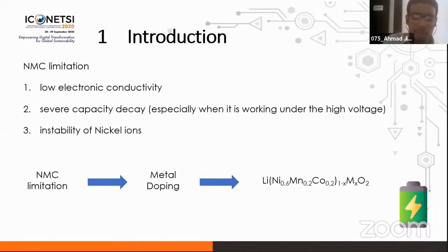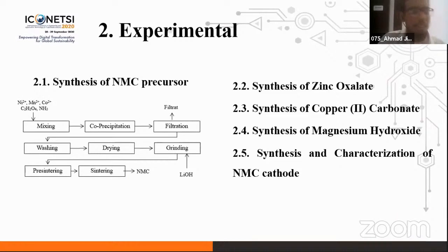In this paper, we performed doping on NMC622 material using zinc, copper, and magnesium as dopant elements with different compositions, and determined the characteristics of each doped sample using X-ray diffraction analysis. For the experiment, first, synthesis of the NMC precursor. Nickel sulfate, manganese sulfate, and cobalt sulfate were dissolved in aqueous solution and stirred until homogeneous. Ammonia and oxalic acid solution were added and stirred. The slurry was filtered and the precipitate was washed until it reached neutral pH. The residue was dried in an oven for 12 hours. This precipitate was labeled as the NMC precursor.